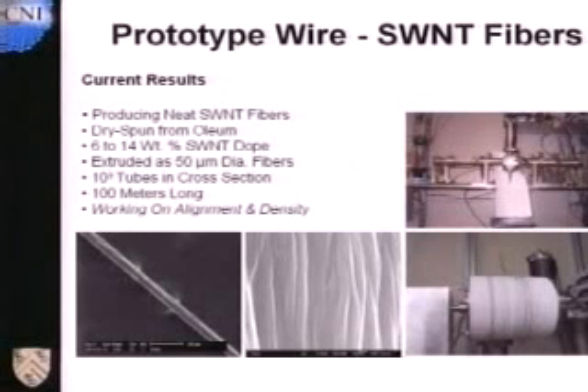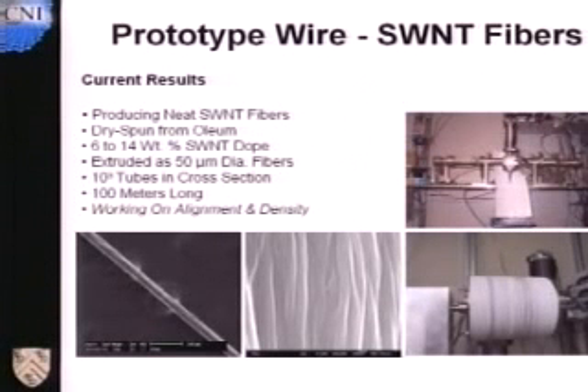The other major part of making a quantum wire from these, after we are able to produce, for instance, pure 10,10 metallic tube production, is to assemble or crystallize those tubes into continuous fibers. And we've got a start on this using a process which was discovered here about 3 years ago, by which nanotubes will almost dissolve. They will disperse in concentrated acids, superacids, primarily oleum. And by a process very similar to how Kevlar and Zylon are made, you can disperse the nanotubes in the oleum and then spin it out as a thick gel, shown here, through a long, narrow orifice, and take up to 100 meters at a time at this point.